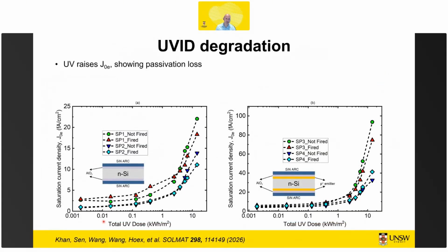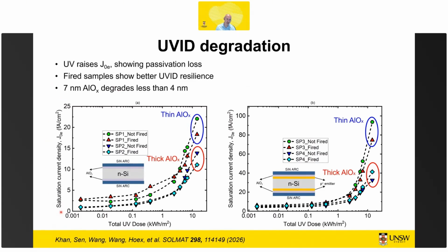If we then look at what is happening with UV-ID, we see that UV dose increases recombination. In this experiment, we tested a thin AlOx film versus a thick AlOx film. We saw that increasing the thickness of AlOx can reduce the UV sensitivity, which is good. It's one of the mitigation methods. We've developed a few more in the lab, which we'll share at a later time. We also see, quite importantly, a difference between lightly doped, which would be the rear of TOPCon with polyfingers, and the front of TOPCon with a boron diffused emitter, where the difference between thin and thick is a lot larger. But we see that the overall extent on an undiffused sample is less, and that's also good news.